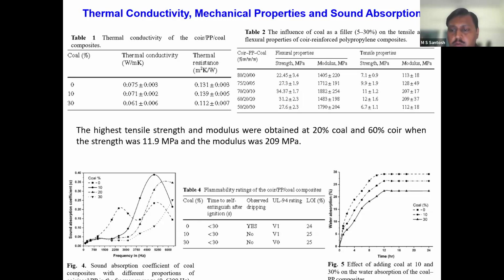In terms of the water absorption, we can clearly see that the 10% has a higher water absorption ability compared to the 30%, whereas coal as an individual material has the highest water absorption property. But when you look at the blending of the materials, 10% eventually plays a significant role compared to the 30%.